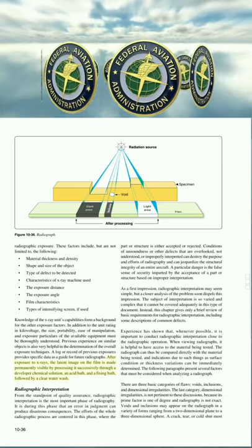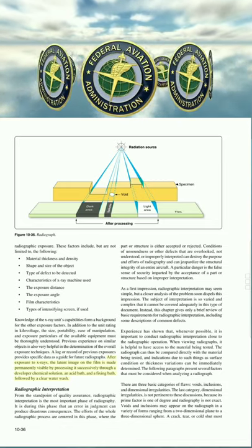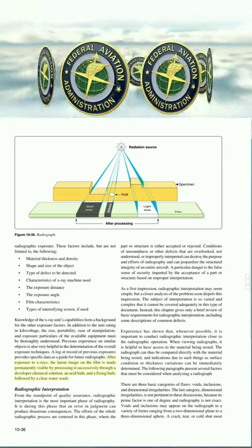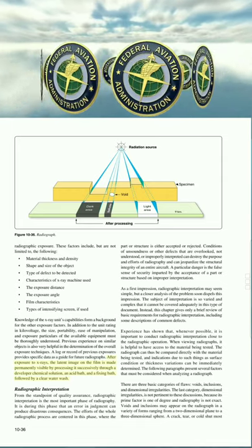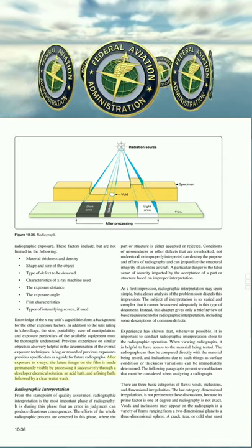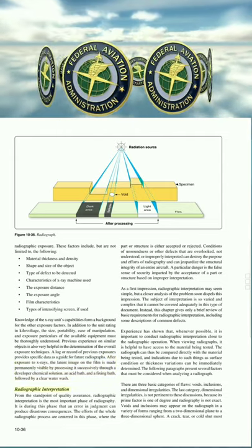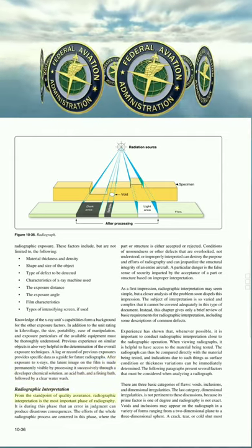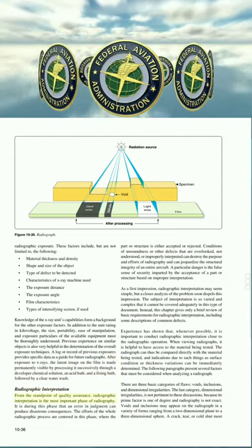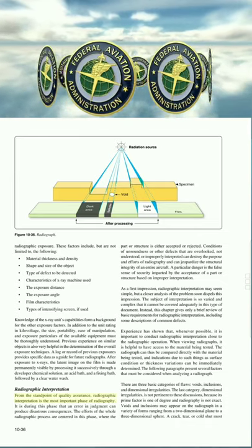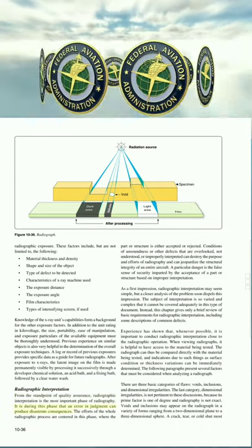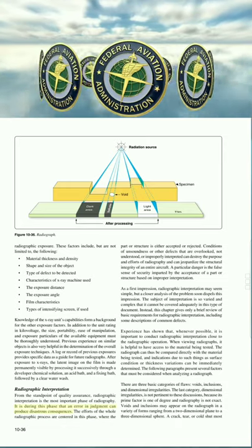After exposure to X-rays, the latent image on the film is made permanently visible by processing it successively through a developer chemical solution, an acid bath, and a fixing bath, followed by a clear water wash. Radiographic interpretation. From the standpoint of quality assurance, radiographic interpretation is the most important phase of radiography. It is during this phase that an error in judgment can produce disastrous consequences.